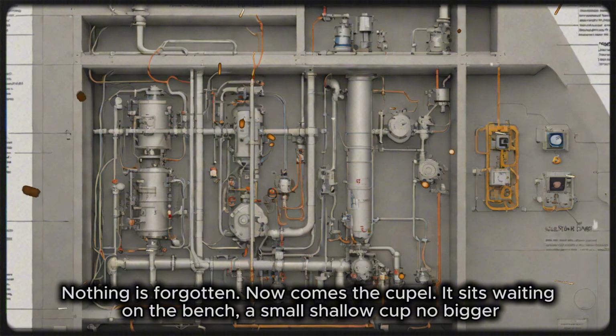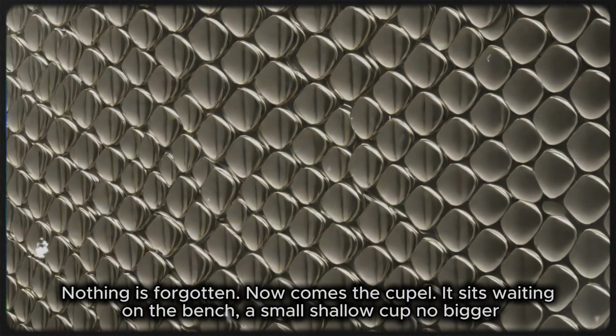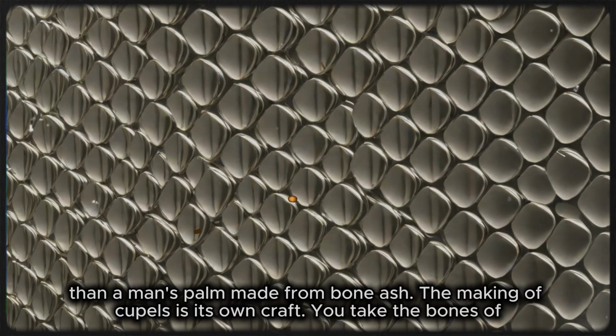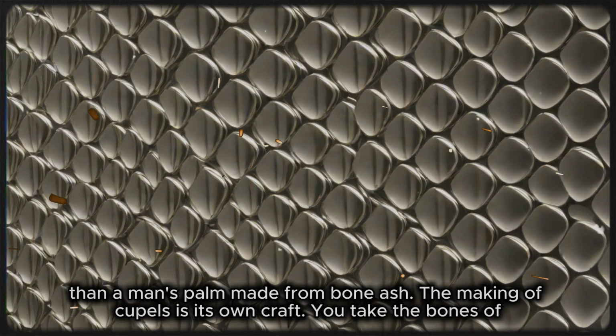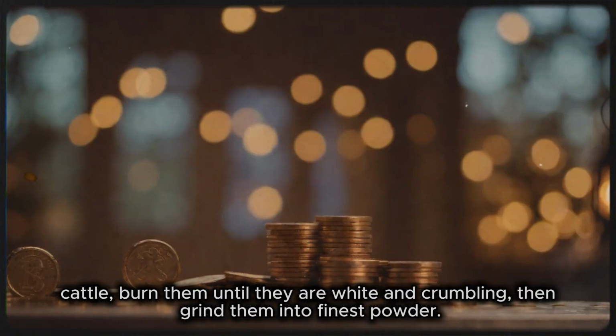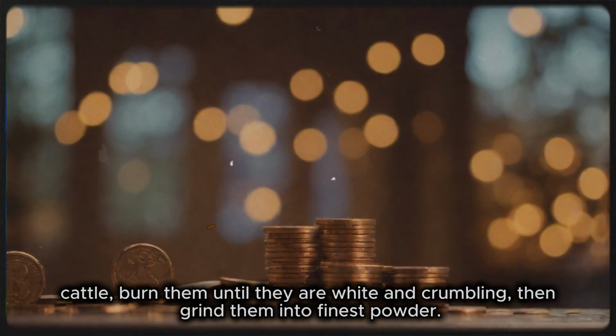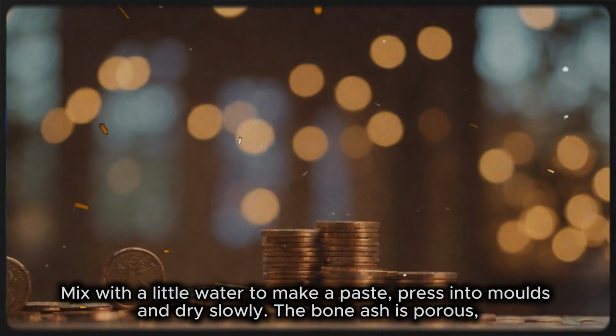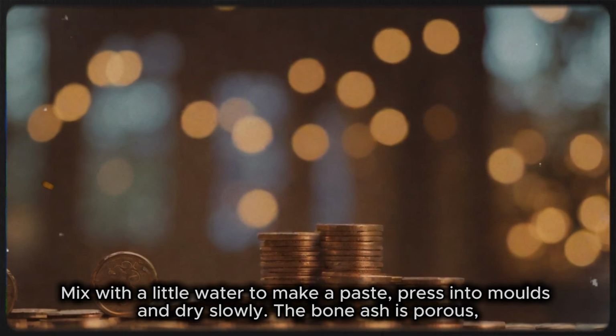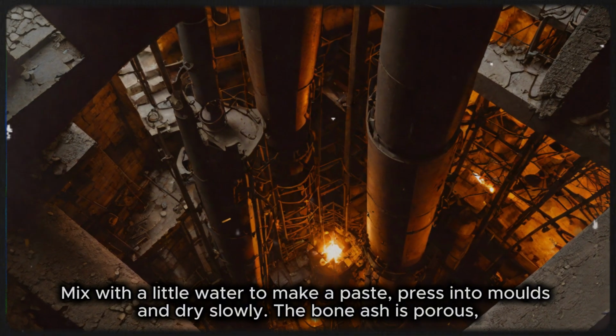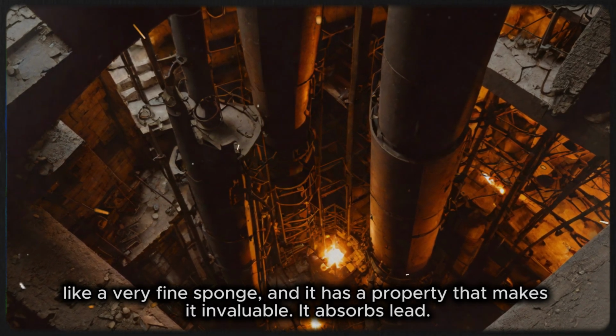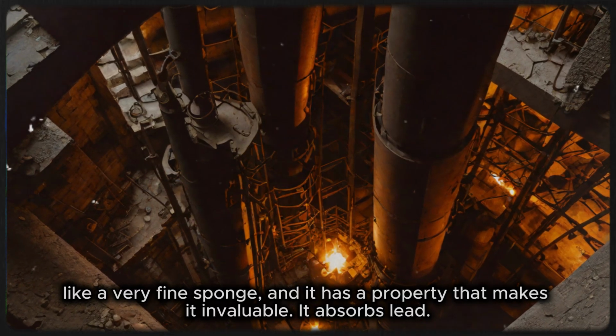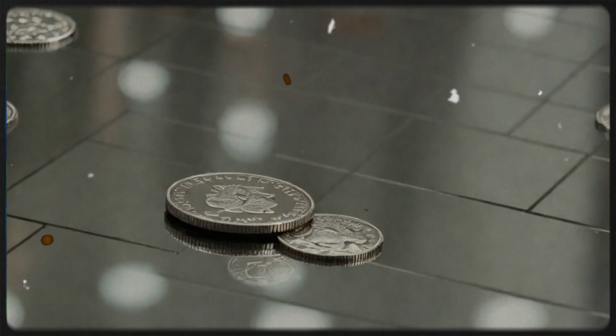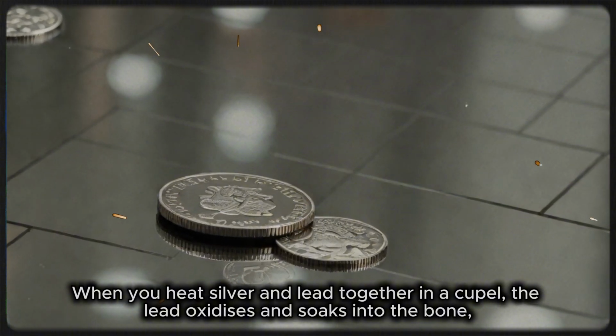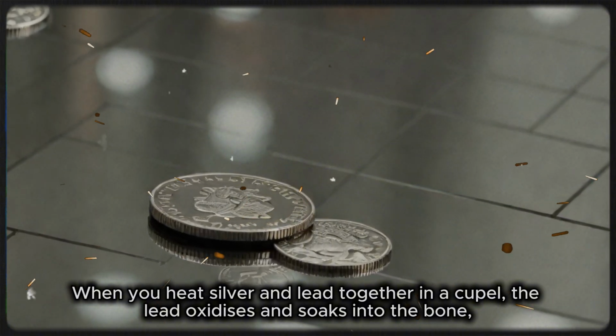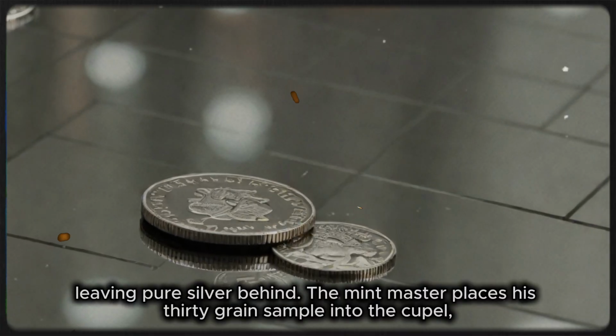Now comes the cupel. It sits waiting on the bench, a small shallow cup no bigger than a man's palm, made from bone ash. The making of cupels is its own craft. You take the bones of cattle, burn them until they are white and crumbling, then grind them into finest powder. Mix with a little water to make a paste, press into molds and dry slowly. The bone ash is porous, like a very fine sponge, and it has a property that makes it invaluable. It absorbs lead. When you heat silver and lead together in a cupel, the lead oxidizes and soaks into the bone, leaving pure silver behind.